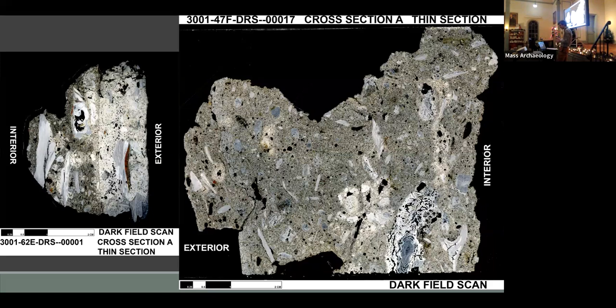Interestingly enough, five samples contain two or more layers of tabby daub, with the first, innermost layer smoothed to produce a flat surface onto which a second layer or coat was added. In some of these samples, the two layers appear to be compositionally the same, so not a finishing coat. But in one sample, there are clear differences. In the sample on the left here, the exterior layer contains less sand aggregate and has a pure lime binder, likely a stucco or a finishing coat to protect the interior fabric.